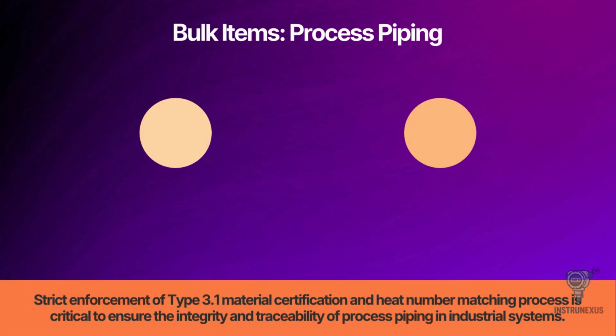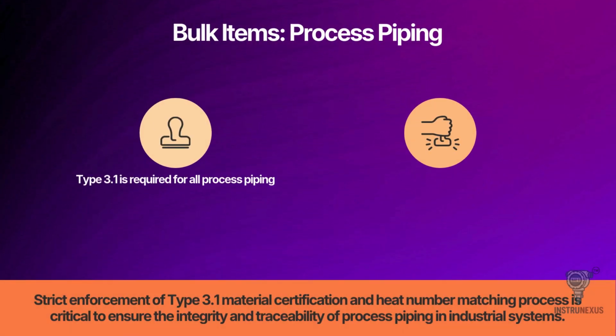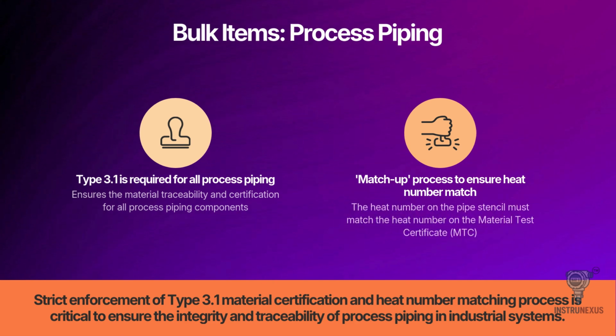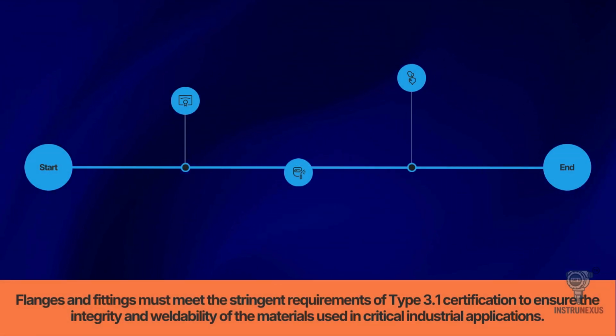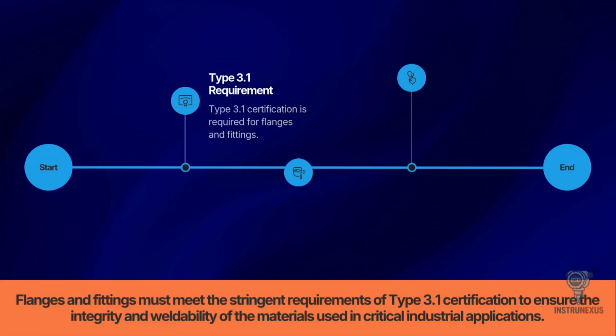Now let's look at process piping. Type 3.1 is required for all process piping to ensure material traceability. But for piping, the paperwork is only half the battle. You need a rigorous match-up process. The heat number stenciled on the physical pipe must match the heat number printed on the Material Test Certificate (MTC). Strict enforcement of this 3.1 certification and the physical match-up process is the only way to ensure the integrity of your piping network. Similarly, for flanges and fittings, Type 3.1 certification is required.